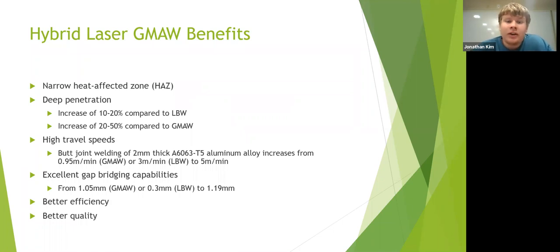Some of these benefits are that it has a very narrow heat affected zone, and this is the zone that is traditionally the weakest part of the weld. So by reducing the size of it, it will drastically increase the strength. It also has a very deep penetration due to the laser beam welding portion that is contributed to the hybrid. And as you can see, it has an increase of 10 to 20% compared to the laser beam welding, and an increase of 20 to 50% due to the gas metal arc welding processes.